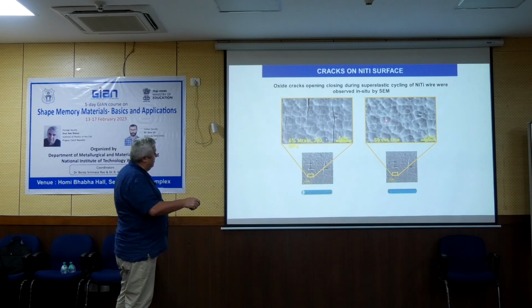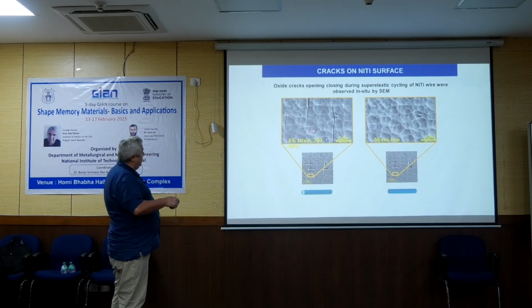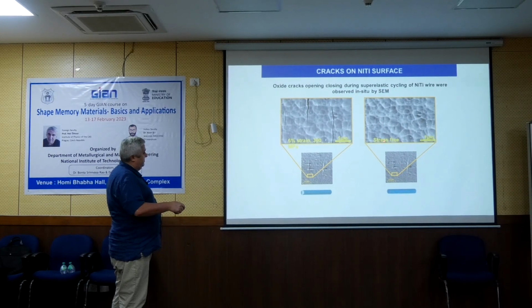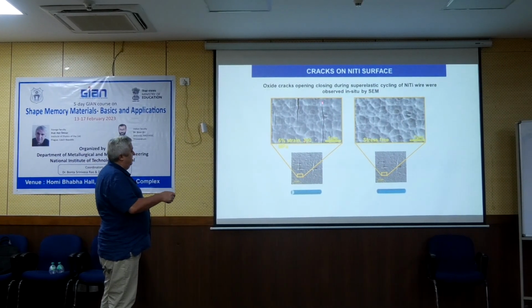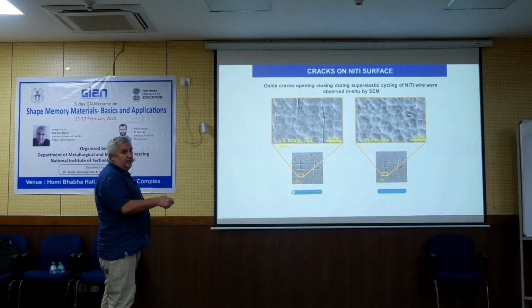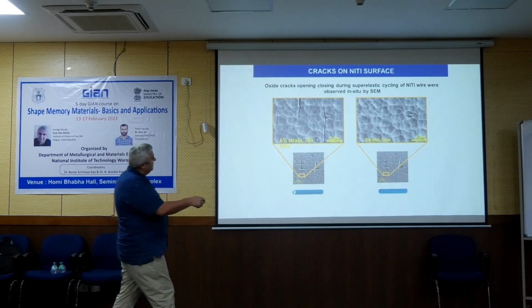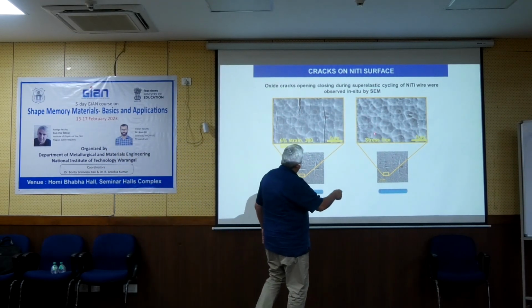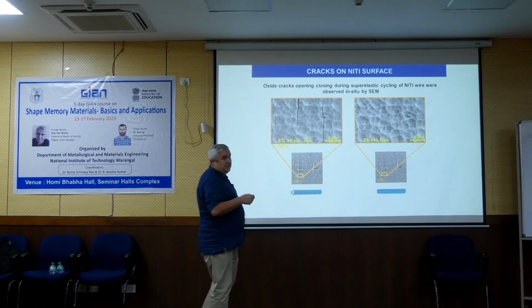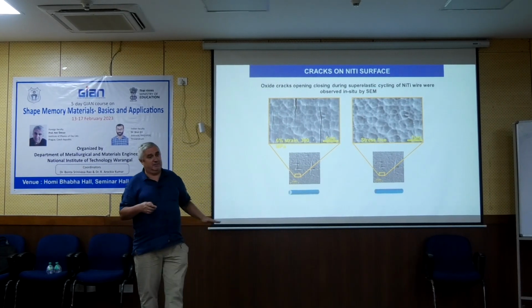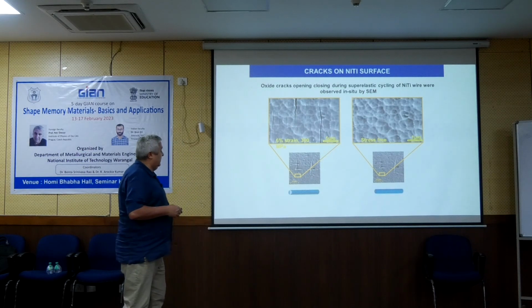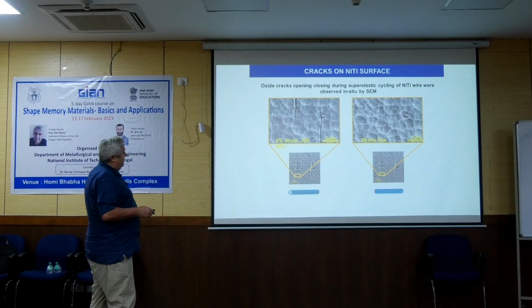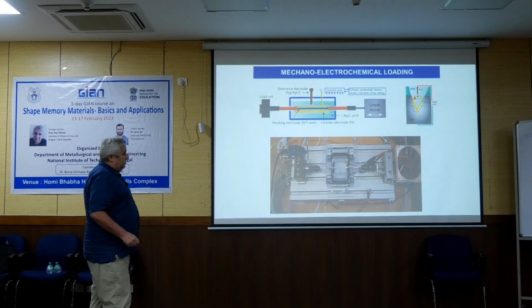This is the demonstration which I mentioned of how the crack looks under stress and without stress. Stress-free, 6% strain. You clearly see the cracks. Here you see almost nothing. But well, you still see them, because they are too big. But if they are smaller, you will not see them even under deformation in SEM.